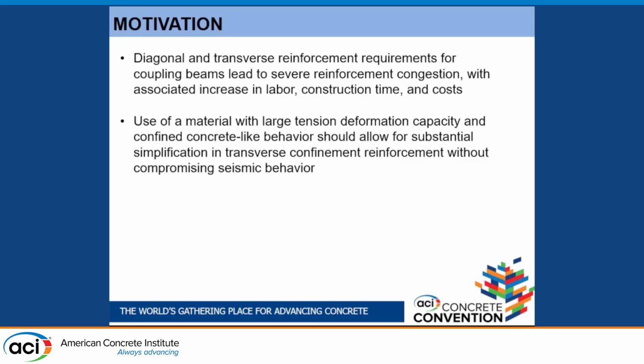If you use a material like one of these high-performance fiber concretes, maybe we can reduce the transverse steel because the material already behaves like well-confined concrete. Also, because of the tensile stress-strain behavior of the material, maybe we can eliminate diagonal bars.